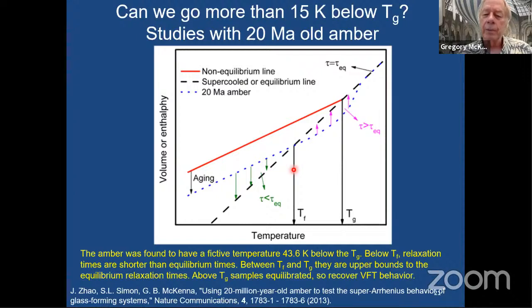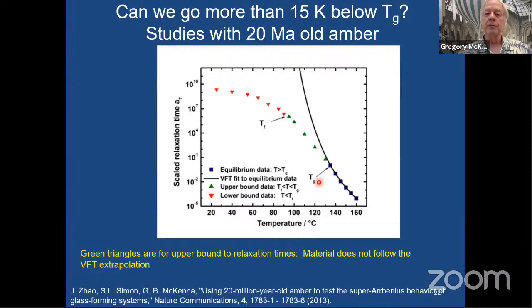Slightly above, still about 20 degrees above the Kauzmann temperature or the Vogel-Fulcher temperature, but still a pretty big window, especially compared to the window that we had previously of like 15 degrees, right? Where we actually aged it into equilibrium up here. And here's the result. The green points are the data in the upper bound condition. So these are longer than equilibrium times. The one here near the fictive temperature arrow should be close to the equilibrium time, because at T equals TF, we have the equilibrium property. So that's where delta equals 0. And that's, remember, what Struik showed seems to govern the dynamics at that point, independent of history.